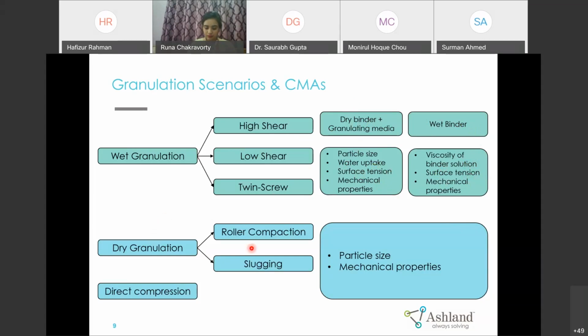Coming to dry granulation, we can do it in two ways. One is roller compaction, and the second one is slugging. Slugging is where you make a bigger tablet with less thickness and then you mill it. So that is called slugging. Both of these manufacturing processes are used in the pharma industry. Their critical material attributes are particle size of the binder and mechanical properties of the binder. And the same thing with direct compression. There also, because we are using a dry binder, particle size of the binder and mechanical properties are very critical.